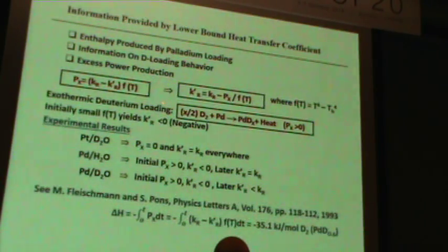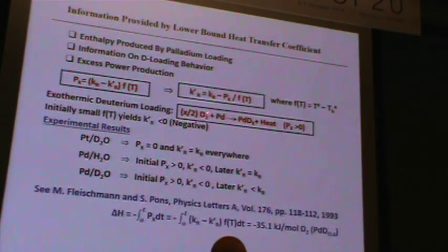So if you do this, you rearrange this equation, you see that early on, this is very small, the temperature of the cell minus the temperature of the bath if you're doing heat conduction. And so it's very small, so you can get a negative value early on. And so it goes from negative and gradually up towards the correct value. This is an equation kind of like y equals a minus b over x.